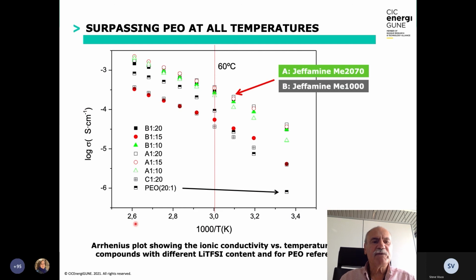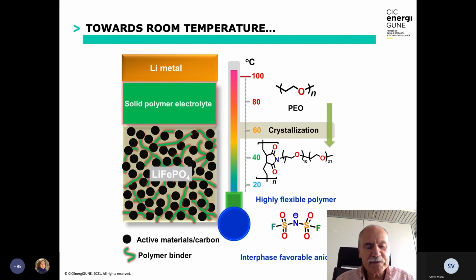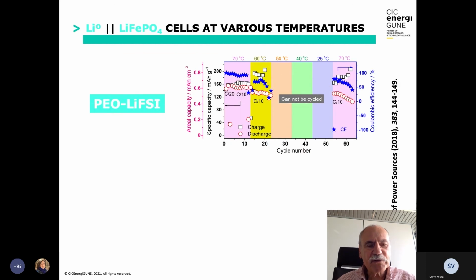And the conductivity of these materials is superior to that of PEO at all temperatures. As you can see, the red arrow, these materials are more conductive than PEO at all temperatures. And in fact, this allows to build batteries. If you build a lithium metal solid polymer electrolyte, either PEO that we want to compare with our Jeffamine polymer, and with a lithium iron phosphate electrode. If you have got a conventional PEO LiFSI battery, you cannot cycle the battery below 50 degrees. There is no cycling possible.